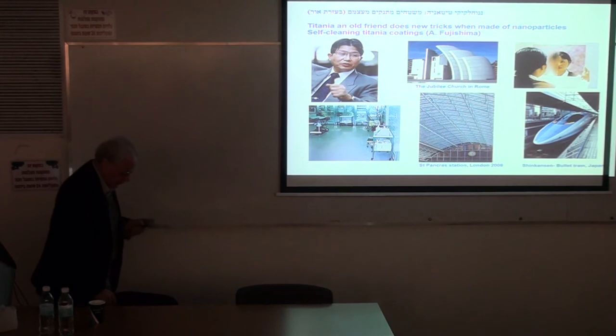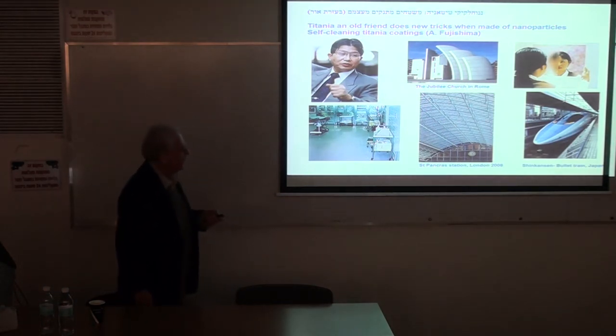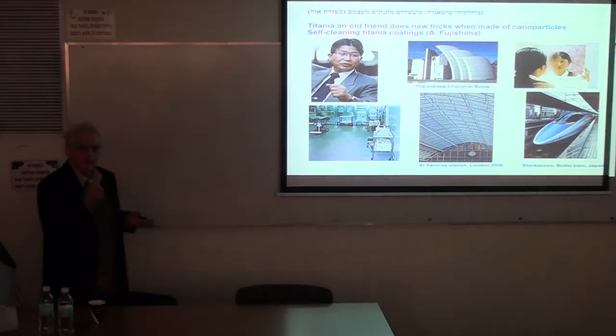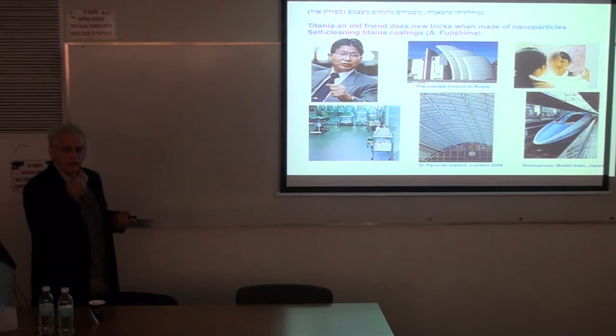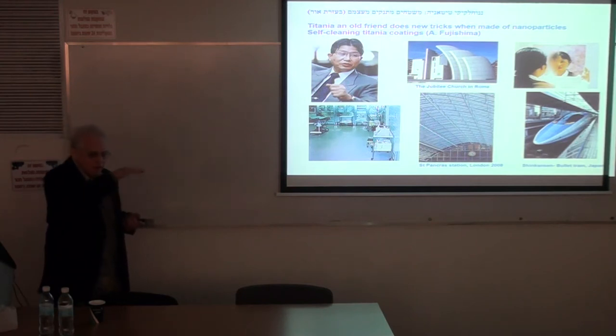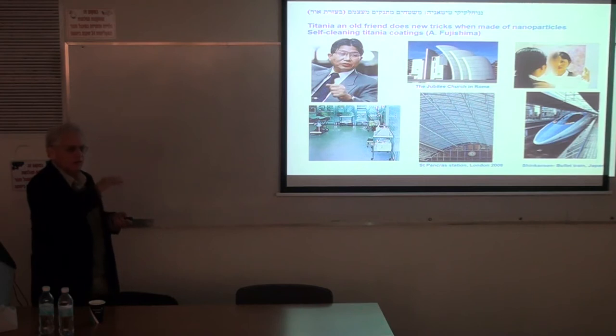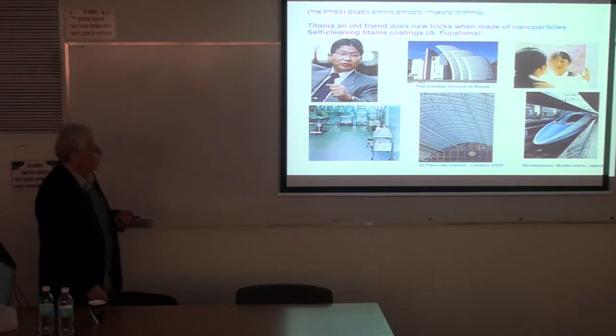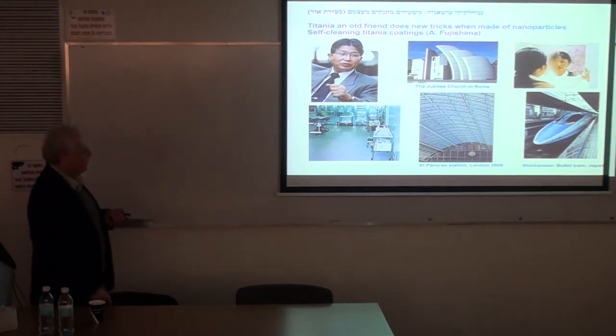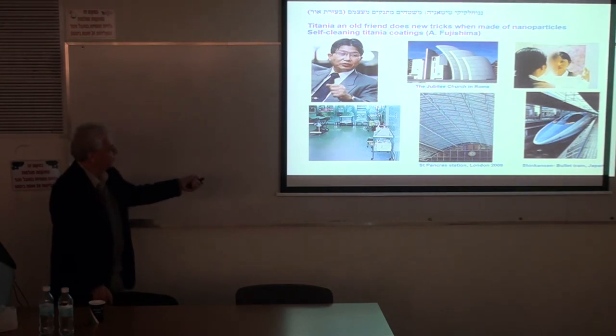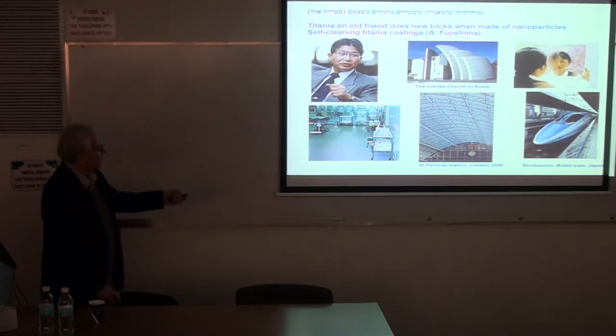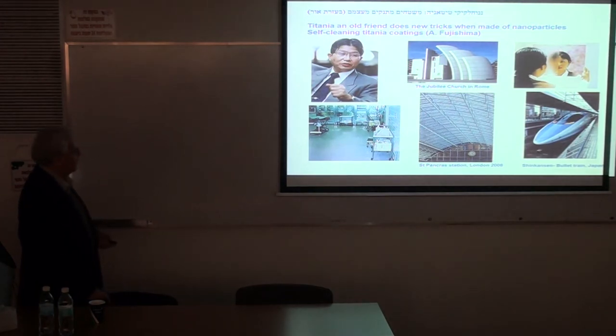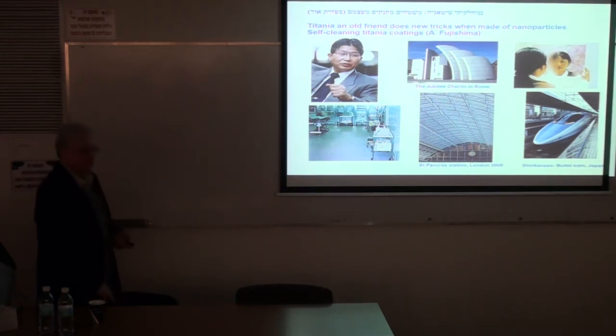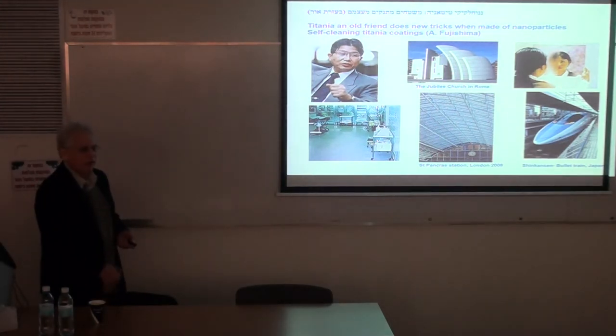not rutile, the other version, anatase titanium dioxide, which can be very easily oxidized, or by absorbing light can oxidize water to OH radicals, and these OH radicals oxidize the surface of the titanium dioxide so that dust cannot stick to it. And if water comes by rainfall, or in a surgery room where you have ceramic plates coated with titania,